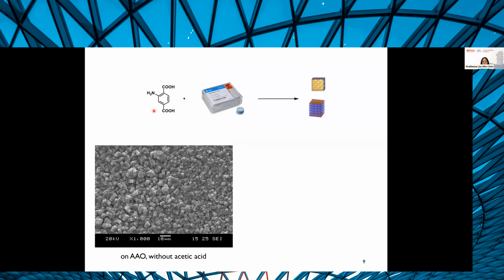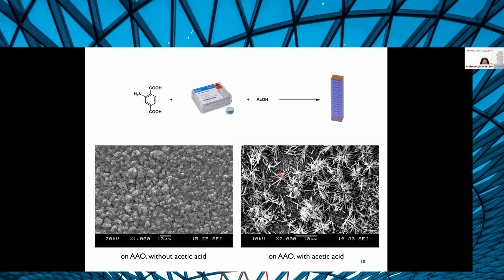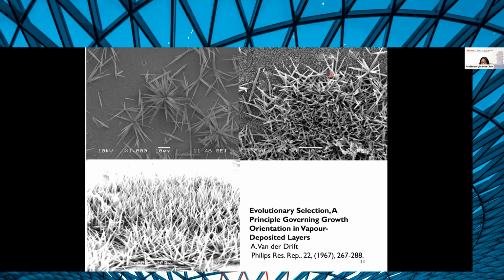So when we took the terephthalic acid and reacted it with our AAO membrane, we got these cuboidal shaped crystals, but in this case, they grow directly on the AAO, and you get full coverage of the substrate. However, if you throw in acetic acid, then you massively slow down the growth, but you also get these microflower type structures all over the place. You get basically these microneedles, but then they start to nucleate and form these flower structures. But then we looked around a little bit, and we found that besides these little flowers, we see patches of these MOF needles that look like blades of grass. And if you look carefully towards the edges of these patches, you get these needles that are splayed out a little bit more.